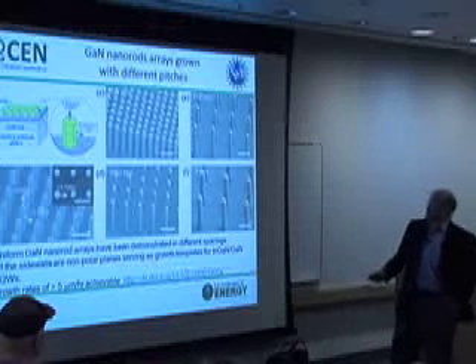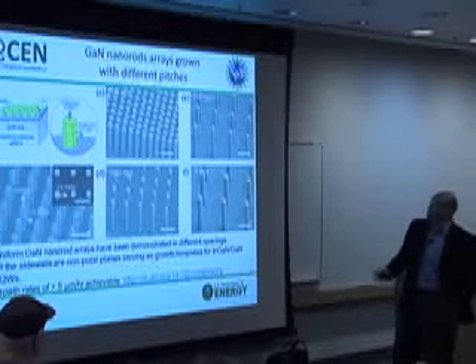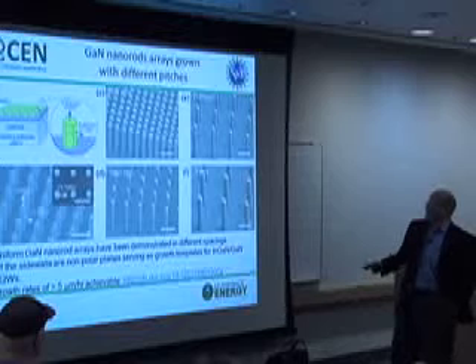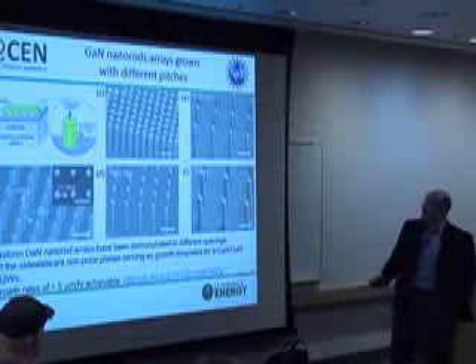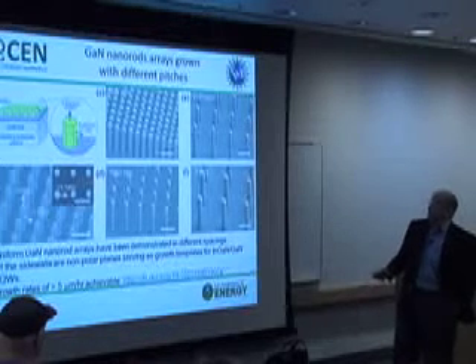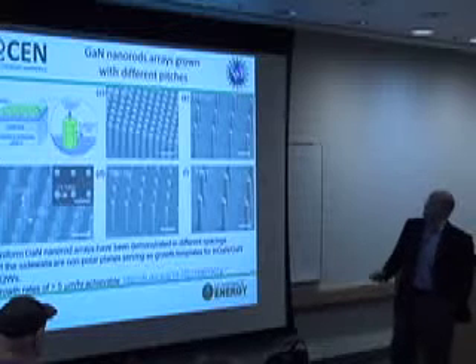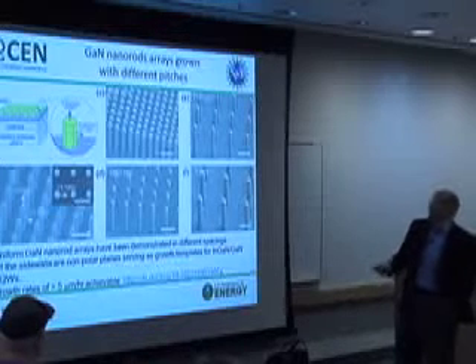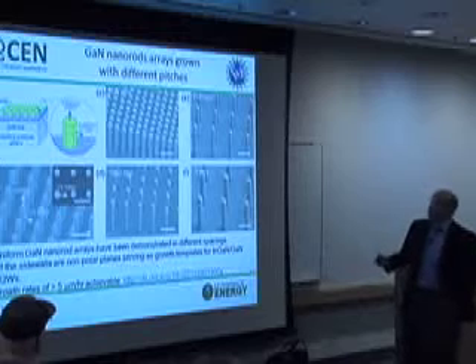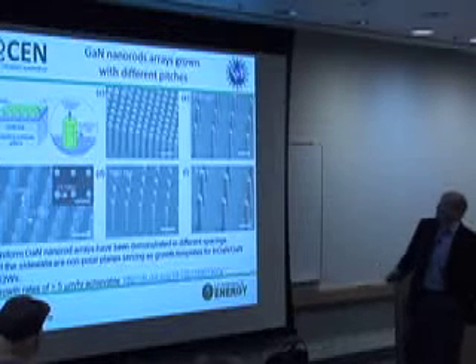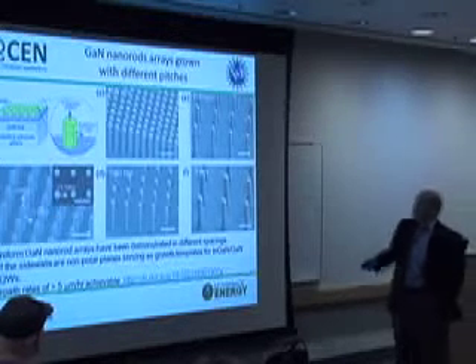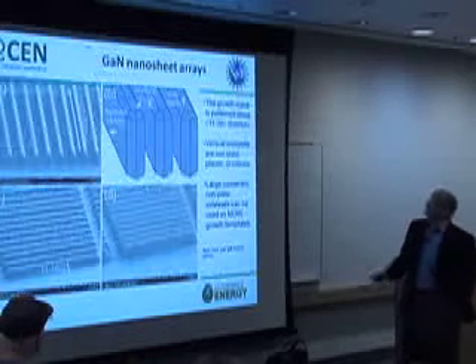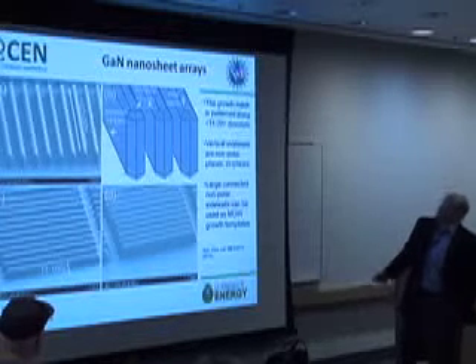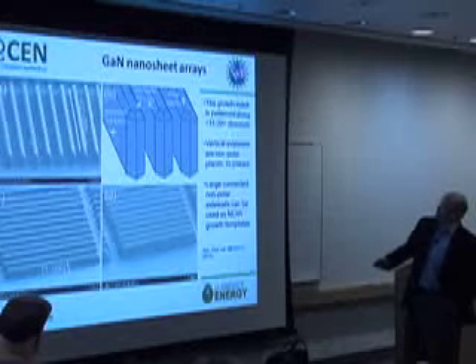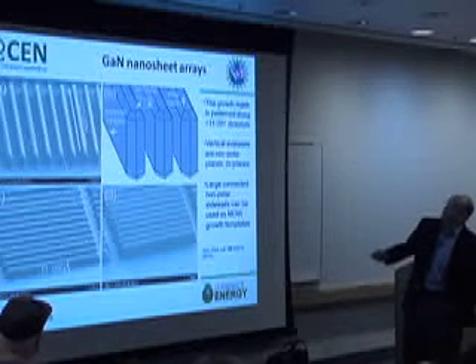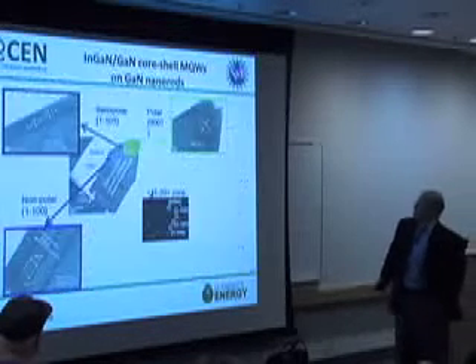Now, recently we've developed a continuous way of growing, that is to say where we continuously feed the reactants into the reactor, and we get fairly high growth rates. Previously, we were hindered by the kinetics of growth to fairly low growth rates, but now we can grow at rates that are comparable to epitaxial growth. Similarly with the nanosheets. Well, there's just an example of the kind of nanosheets that we can form.